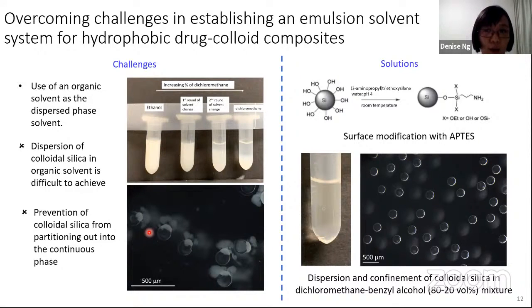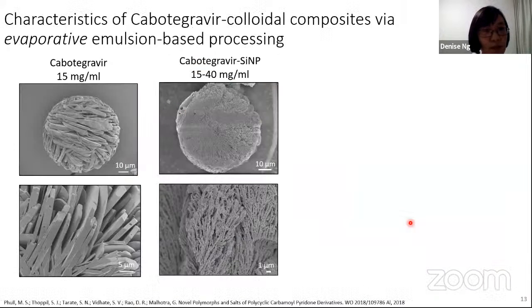So to overcome this, we propose two solutions. Firstly, we surface modify our colloidal silica using silane chemistry with (3-aminopropyl)triethoxysilane. And we disperse and confine them in a co-solvent mixture of dichloromethane and benzyl alcohol. And here we can see that we are able to do that quite successfully. The droplets here actually appear transparent because of the matching of the refractive indices between the colloidal silica as well as the co-solvent mixture. Then we perform the same evaporative emulsion-based processing using a model hydrophobic drug, which in this case is cabotegravir, a hydrophobic antiretroviral drug.